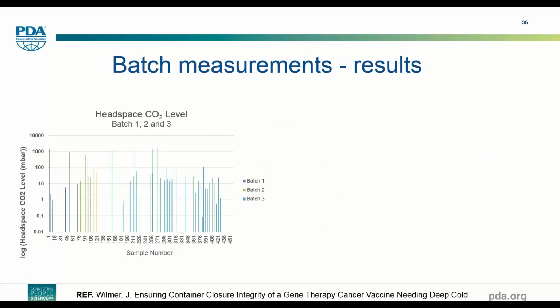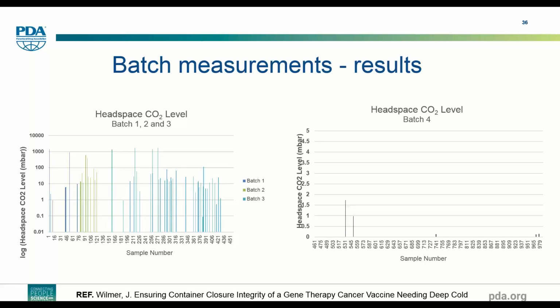And if you look at the results of the CCI testing of these GMP batches, so here's the result testing batches 1, 2, and 3. The CCIT test method, again, was developed and validated based on CO2 detection. You see issues, CCI issues in the first 3 batches, but not in the last batch.